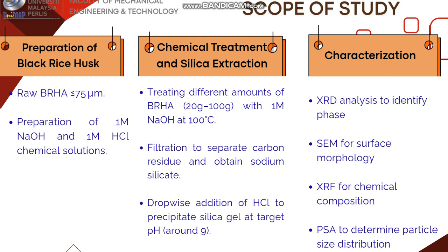The scope of study. Our research involved three main stages. Preparation of BRHA, which has to be sieved below 75 micrometer. Chemical treatment: BRHA is treated with 1 mole of sodium hydroxide at 100 degrees Celsius, followed by acid precipitation using 1 mole of hydrochloric acid at pH 9. The characterization uses XRD, SEM, XRF, and PSA to analyze the extracted silica and recovered carbon.